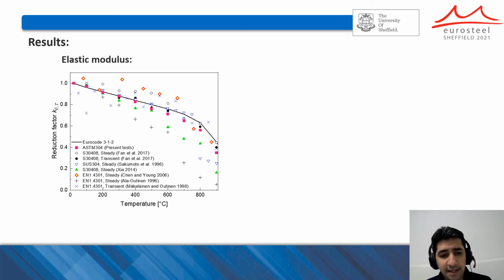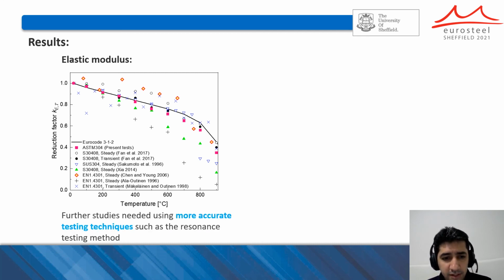This is due to the fact that measuring elastic modulus using stress strain curves is a very delicate experimental task, which is very prone to error. And we suggest that in future studies, more accurate testing techniques such as the resonance technique be utilized to gain more accurate and more reliable results for elastic modulus.